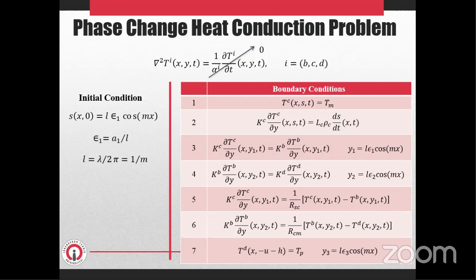The heat conduction equations are solved for obtaining temperature fields in the solidified shell, coating layer, and mold by using these thermal boundary conditions. Equation 1 states that the freezing front is isothermal at the fusion temperature, while equation 2 defines an energy balance between the heat conducted away from the advancing interface into the solidified shell and latent heat released during solidification. Equation 3 and equation 4 state that the heat flux from casting to the coating and coating to the mold must be continuous.